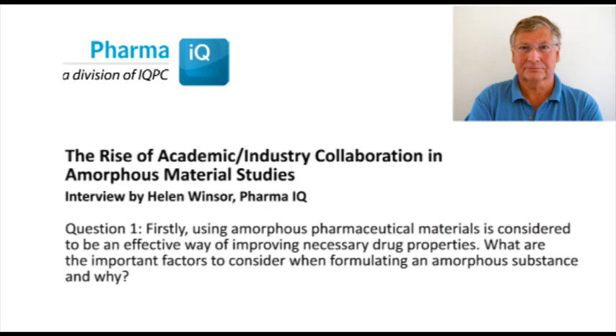Consequently, the thermodynamics are also very important to consider, because very recent fundamental research has shown that there is a possible connection between the thermodynamic stability limit and the evolution of the mobility. It is thus necessary to use several complementary techniques to probe relaxation, spectroscopy, calorimetry, and also structure, of course, to check the degree of homogeneity, for example, or to catch nucleation. It is also very important to predict the value of Tg. It is what I can say at the moment on this problem of important factors to consider.